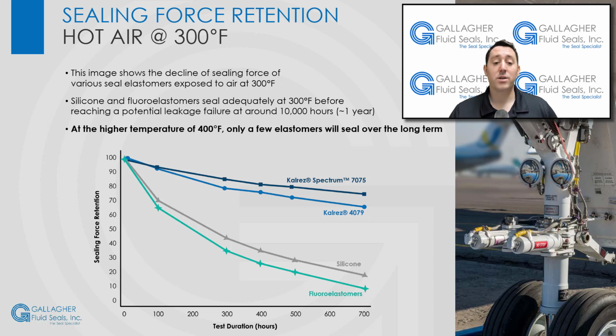Even so, as you can see in this graph, after 10 days of testing, the Viton sample loses considerable sealing force and crosses below Kalrez compound force plots. At the 200-day test mark, the fluoroelastomer has lost all sealing force. Kalrez 4079 exhibits excellent retained sealing force beyond the actual test. Extrapolation of the plot indicates service life of over 10,000 hours.